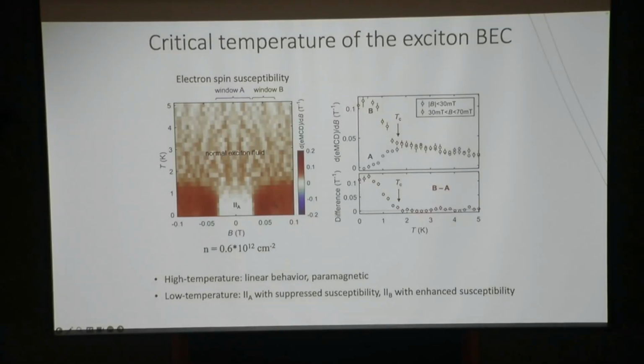Now we think we have this two-component exciton condensate. We can also ask, how does it change with temperature? What's the critical temperature of the condensate? So we can measure the spin susceptibility with small magnetic field, but also with different temperature. And then we can do vertical line cuts for the 2A region and the 2B region. So what you can see is, in the 2A region, the susceptibility is strongly suppressed. In the 2B region, the susceptibility is strongly enhanced. And there's a TC around 1.5 Kelvin, and then they collapse into basically paramagnetic behavior. So this is somewhat consistent with the condensate disappearing at finite temperature. This is at a fixed density.